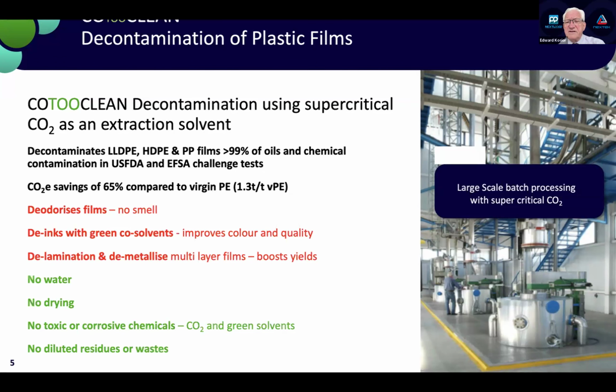We've conducted a series of challenge tests that comply with US FDA and EFSA to estimate these levels. This performance is quite uniform across all of those polyolefin materials, and that's rather unique for a decontamination process. We know that using a supercritical CO2 extraction process is energy efficient, and it saves something of the order of 65% CO2 emissions compared to virgin PE, so roughly a saving of 1.3 tonne per tonne of virgin PE that would be replaced by this.